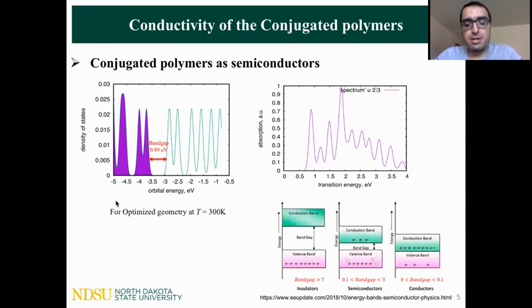As mentioned by Raju and also Zhaofan, maybe the most important material available here is the density of states and the absorption of the energy. As you know, for semiconductor materials, we expect to have a band gap between 0.1 and 3. Usually this value is reported between 0.8, according to my best knowledge, to 1.8 for conjugated polymer models with different structure. Here at room temperature, the band gap is observed at 0.89 electron volt for this conjugated polymer model, as you can see in the top left figure.